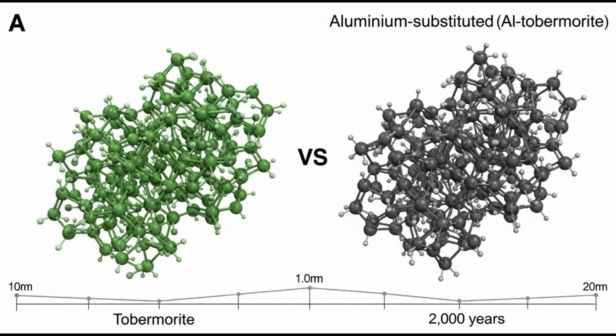Compressive strength measurements increased by 20 to 30% compared to estimated original strength. The concrete literally got stronger over 2,000 years of seawater exposure. Aluminum-substituted tobermorite also forms. This occurs when aluminum from the pozzolana incorporates into the crystal structure. Aluminum-substituted tobermorite is even more stable than regular tobermorite, more resistant to dissolution. It forms in seawater through complex reaction between pozzolana, lime, and seawater components.